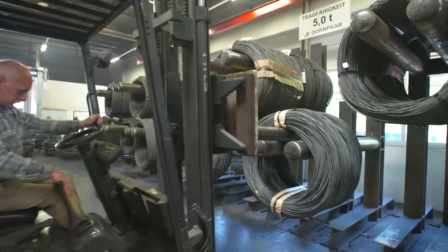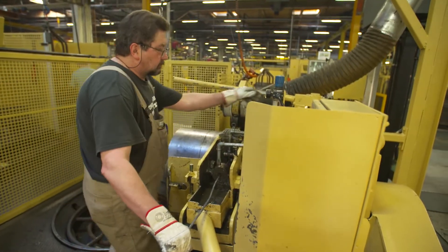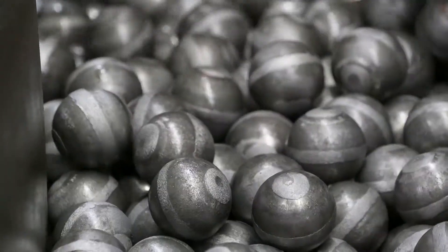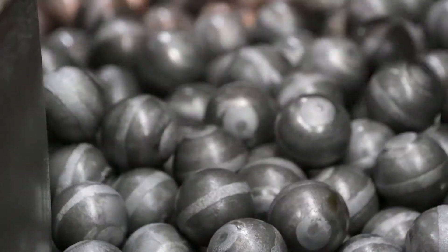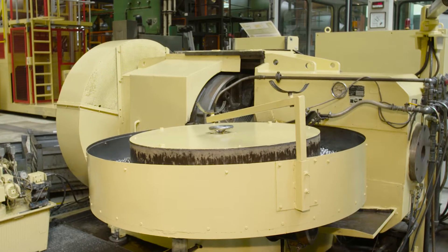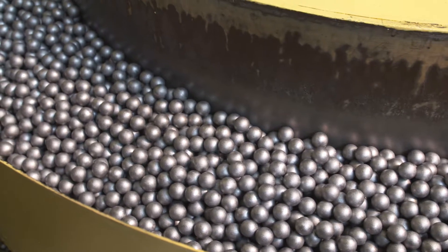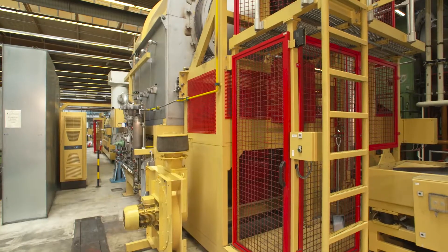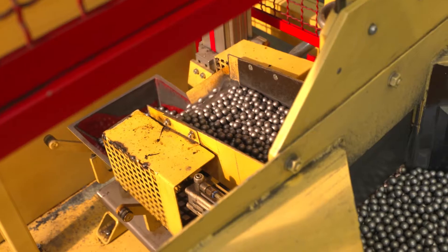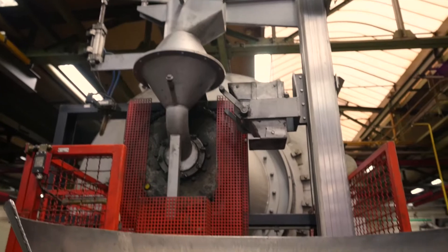The story of a ball starts either in the forging shop or, as in this case, with wire coils that are delivered to the Homburg plant. The wire is cut into sections and then pressed together, a process that results in a blank having a so-called Saturn's ring and a pole. During the subsequent flashing procedure, both the Saturn's ring and the pole are removed to create a round shape. The balls are evenly ground several times and are then ready for the hardening furnace. Hardening is important to give the balls the necessary durability so they will be able to withstand the pressure in the bearing later on.